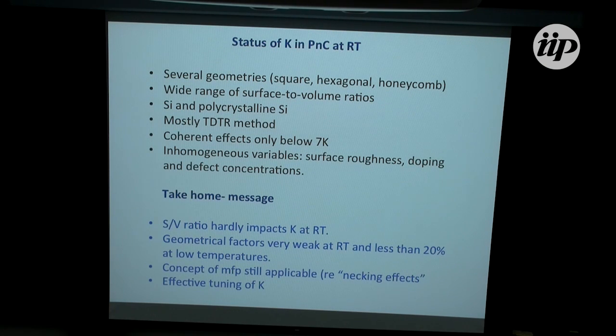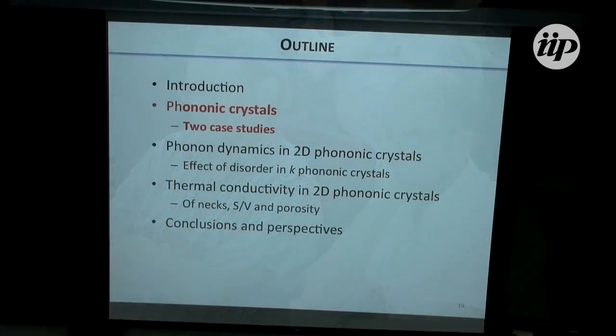The rest of the talk is organized in such a way that I thought I should give you the conclusions first, or at least a take-home message, as it sometimes is called. Our experiments show that the surface-to-volume ratio itself hardly impacts the thermal conductivity. But the geometrical factors, which are very weak at room temperature, can be about a fifth at low temperatures. We also find that the concept of mean free paths still applies, but you need to consider the necking effects. And depending on a combination of surface-to-volume ratio and geometry, you have scope to tune the thermal conductivity of a 2D phononic crystal, which is already significantly lower than the bulk. So, we'll start with two case studies.